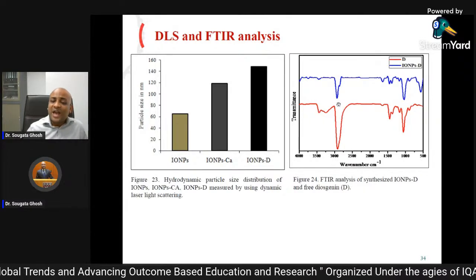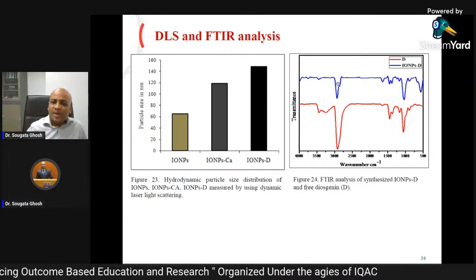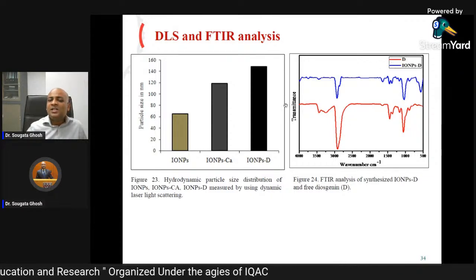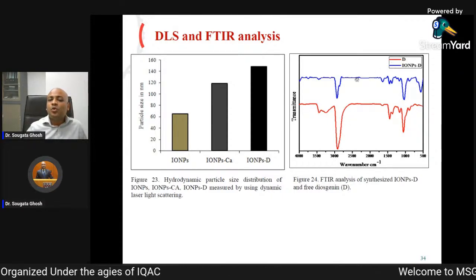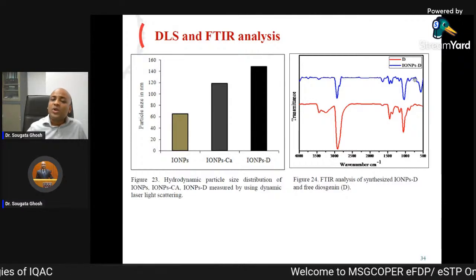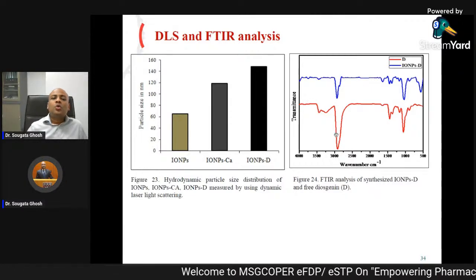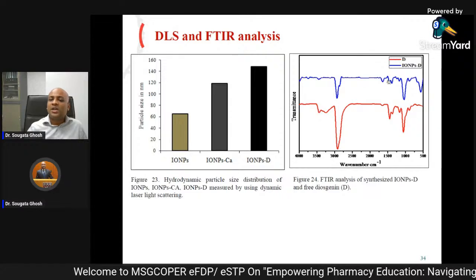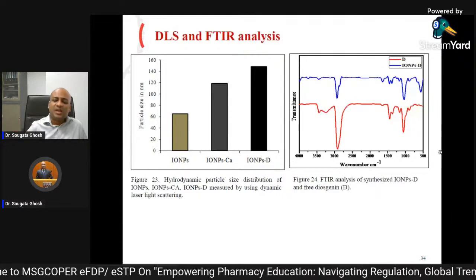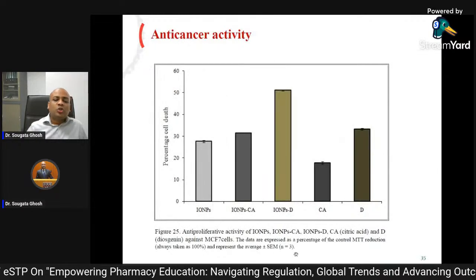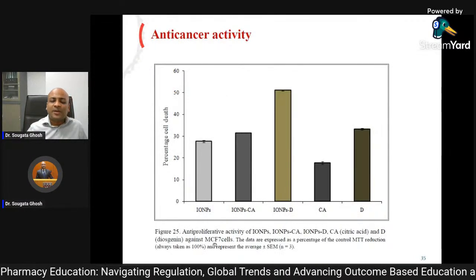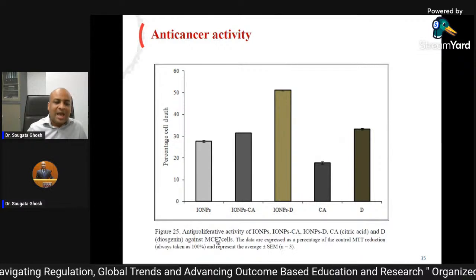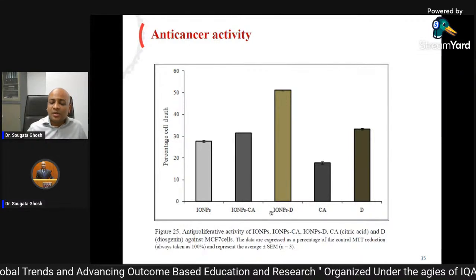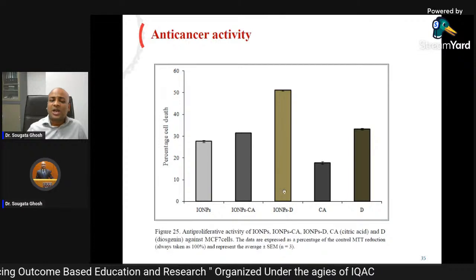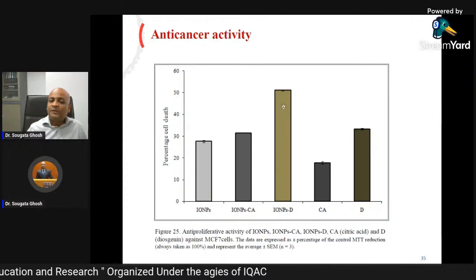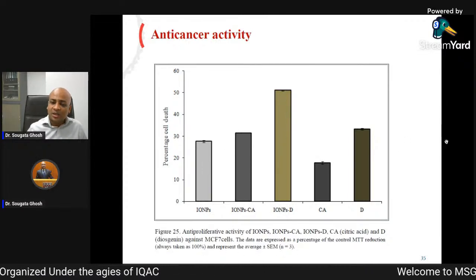We confirmed whether diosgenin was present on that iron oxide or not by FTIR. This red color is the pure diosgenin, and this blue color is iron oxide nanoparticle with diosgenin. So we can see the same peaks of diosgenin over here. This confirms that diosgenin is present in the nanoparticle. We saw the anti-cancer effect against MCF7. This is a breast cancer cell line. And we found that diosgenin functionalized iron oxide was giving the highest activity, around 50% as compared to others.